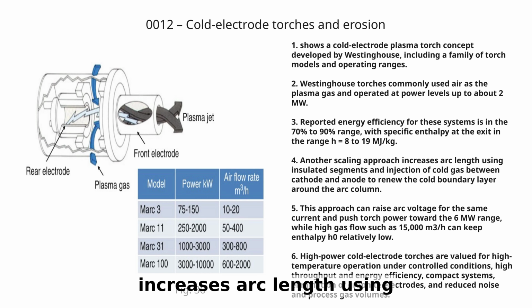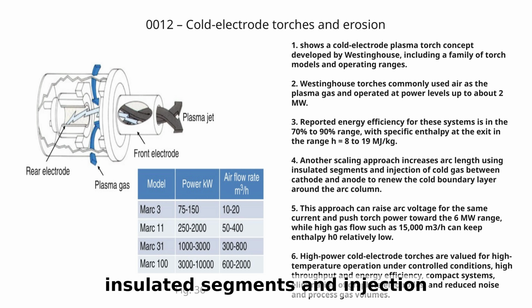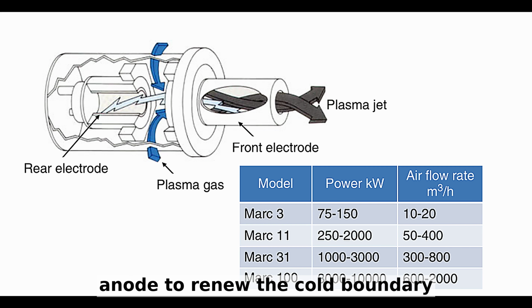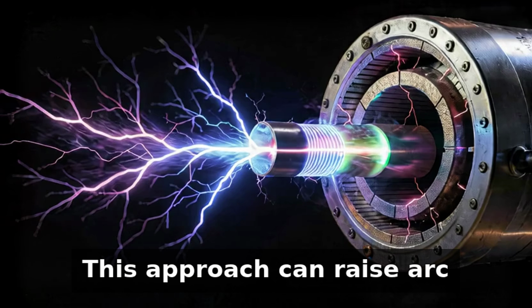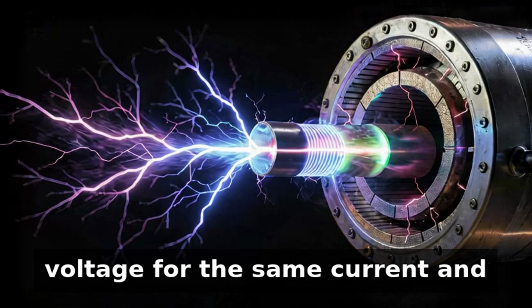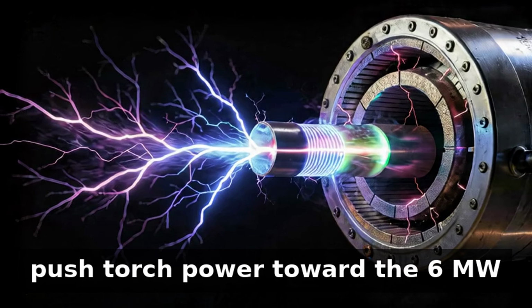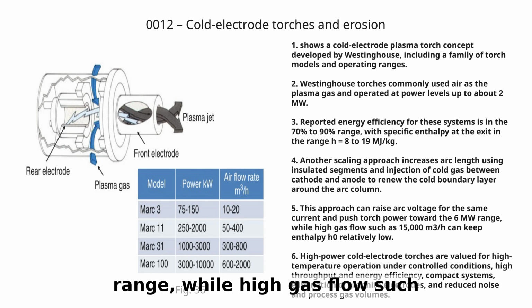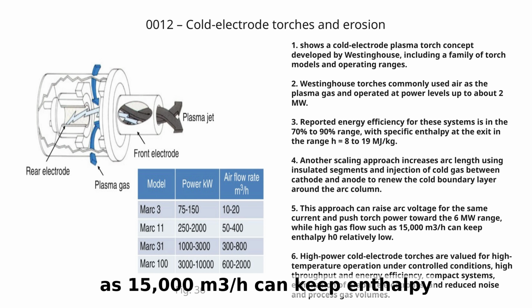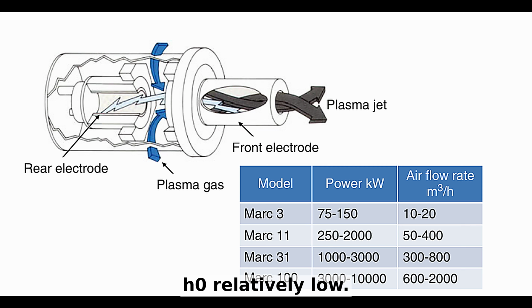Another scaling approach increases arc length using insulated segments and injection of cold gas between cathode and anode to renew the cold boundary layer around the arc column. This approach can raise arc voltage for the same current and push torch power toward the 6 megawatts range, while high gas flow such as 15,000 cubic meters per hour can keep enthalpy H0 relatively low.